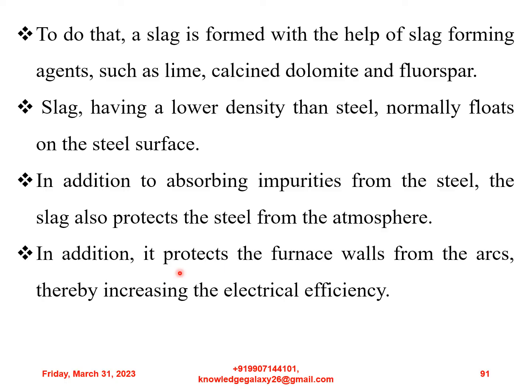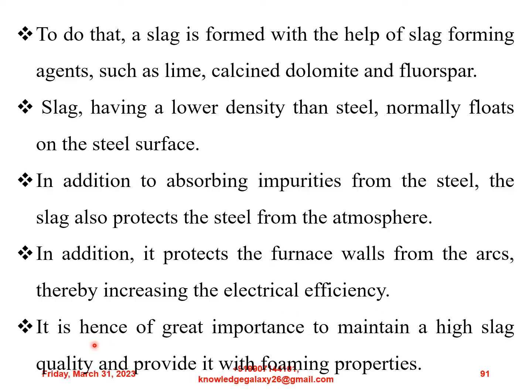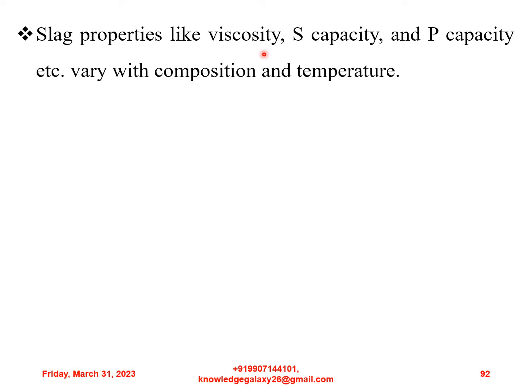In addition, it protects the furnace walls from the arcs, thereby increasing the electrical efficiency. It is hence of great importance to maintain a high slag quality and provide it with foaming properties. Slag properties like viscosity, sulfur capacity and phosphorus capacity, etc. vary with composition and temperature.